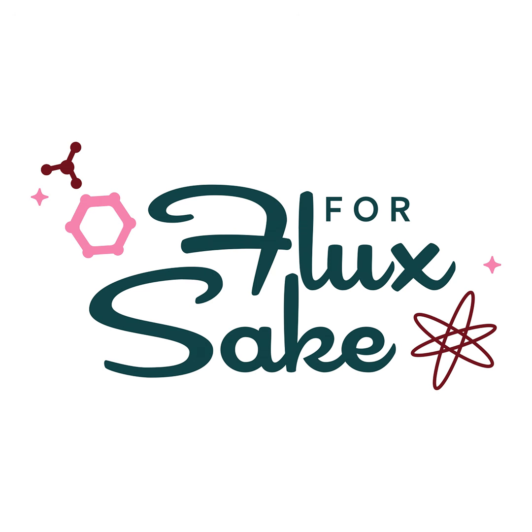And in this case, that's what Karen has got. She has got a calcium crystalline glaze. It's growing crystals for the same reason that the big zinc silicates are growing. It's just that when you use calcium, it makes a much smaller crystal, very subtle, right? And not huge, right? Those zinc ones can grow sort of infinitely big. And so it's just growing crystals.